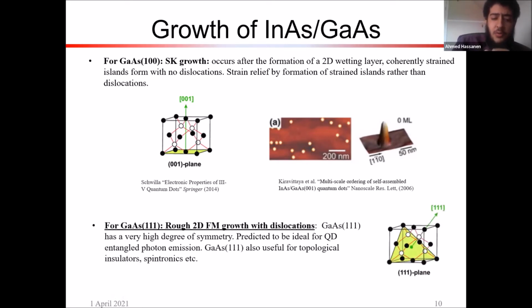But for 111 though, we have two problems because first of all, it proceeds in a 2D fashion, so we're not going to be able to get quantum dots naturally without intervening, and it's also quite rough. So there are two main problems really with gallium arsenide 111 growth, and this is just how the plane looks like.